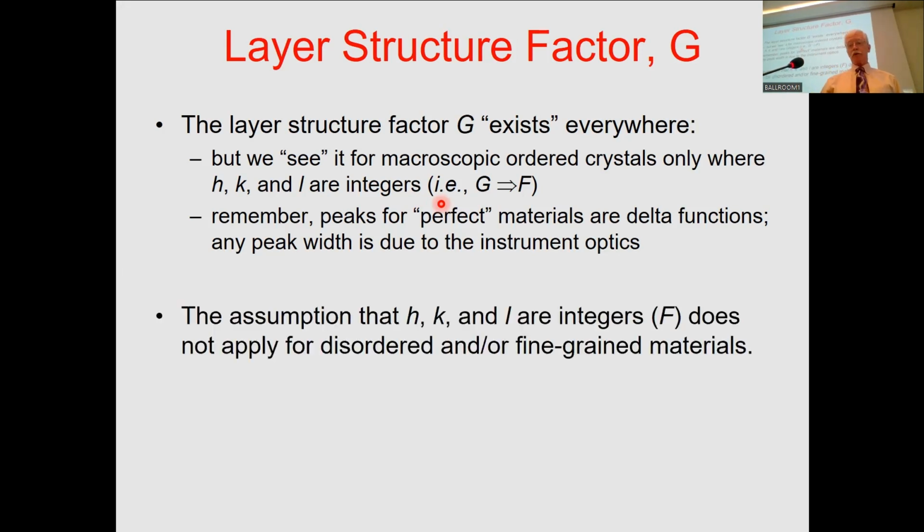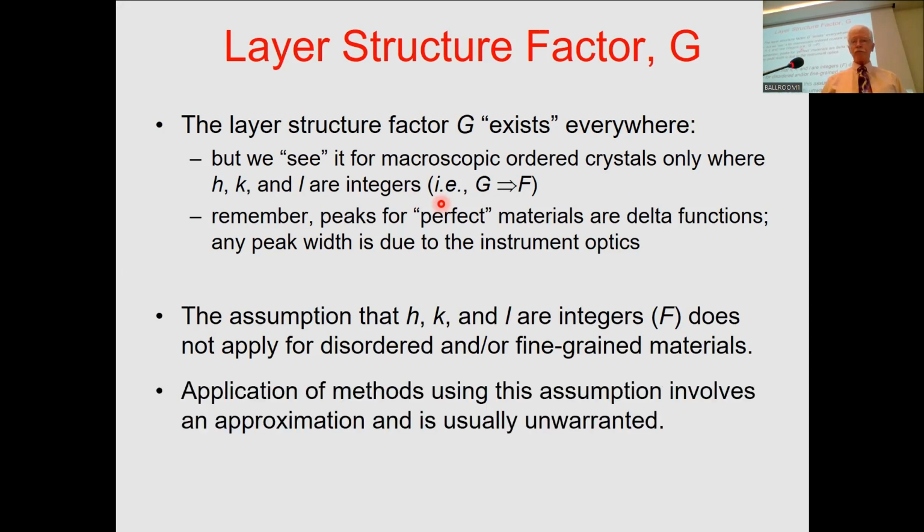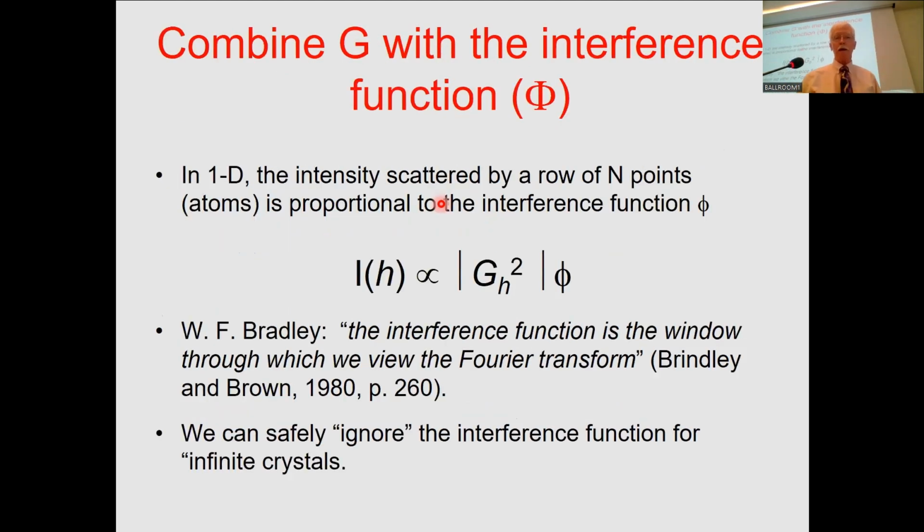This doesn't apply for our disordered materials, and you don't want to use it. So if you're analyzing diffraction data for clay minerals using the Rietveld method, pay attention to what that's doing to your results. Many people say, well, I had a multi-component analysis, the sum was 100%, it must be good. The sum is constrained to be 100%, unless you do some special things.